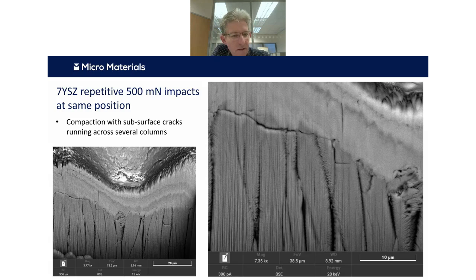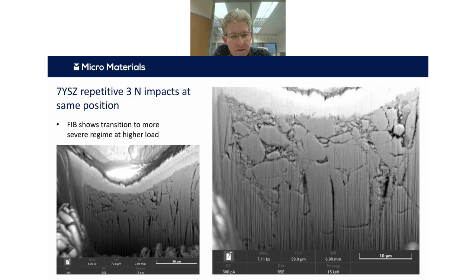If we now look at higher force, in this case the same test, the only difference is that the force is 3 newtons instead of 500 millinewtons. Now we can see a much more extensive crack network, and the columnar structure is really being broken up, transitioning into a much finer scale microstructure and material removal.